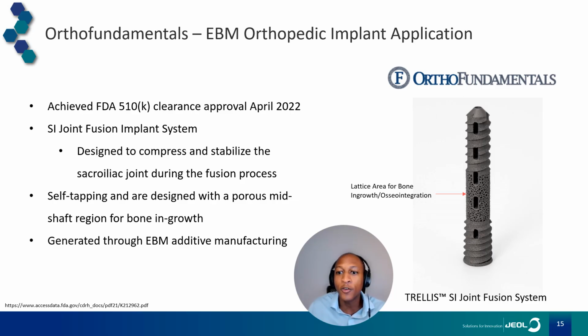We worked with this company to first design a lattice structure, as you can see on the right, by utilizing topology and optimizing the lattice strut size and pore size to get excellent bone ingrowth. Also, to confirm and make sure that the lattice structure had the appropriate mechanical properties to be used in this application. After we worked with this company, we were able to qualify this lattice structure, and print these implants for production, and we were able to achieve an FDA 510(k) clearance in support of Ortho Fundamentals, approved through the FDA in April of 2022.